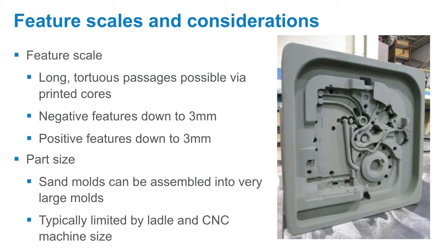One of the things that's interesting, unlike what we were talking about with investment casting, the inability to access long, tortuous channels, being constrained by the fact that you're building up that mold structure using fluid flow, because we're actually able to print every surface here, you can make these long, tortuous passages. So you see a lot of integrated hydraulic lines, coolant lines, a lot of highly multifunctionalized geometry as a result of this.